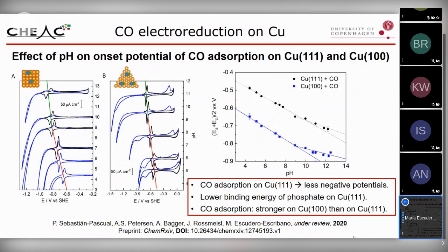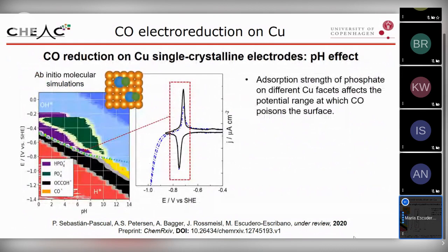So this is something that we could more or less hypothesize from experiments, but we have combined this work with ab initio molecular simulations from Jan Rossmeisl's group, and I won't go into detail, but everything is very consistent between experiments and theory. The great thing about doing these very well-defined experiments is that we can really compare, because we are looking at exactly the same kind of electrochemical interface.